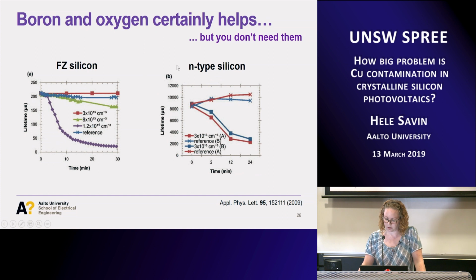And then the other experiment we made was that, well, let's use not boron as a dopant, but N-type silicon. So these were phosphorus-doped silicon. And in those experiments, what we found out is that actually you have to have really high quality. A similar thing happened as in float zone. So in normal N-type silicon, we didn't see degradation. But if we go high enough in lifetime, so high quality enough